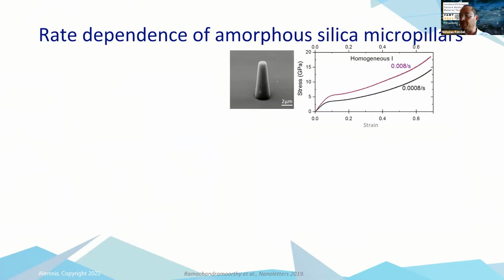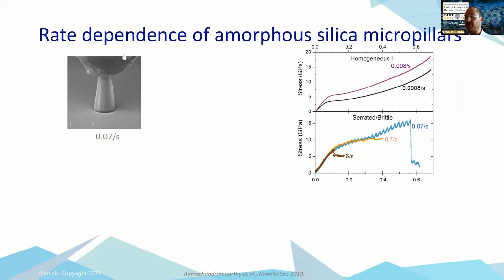And just to show you why that's useful, this is a fused silica pillar. If we deform this pillar very slowly, it's glass, we get a ductile result, right? So at 0.0008 per second and 0.008 per second, we've got very ductile deformation, which is normal. If you deform glass very slowly, it deforms in a plastic way. If we go to the next order of magnitude, 0.07 per second, you can see now that we're failing the pillar and we've got some serration. So we're actually seeing the ductile to brittle transition of the glass.